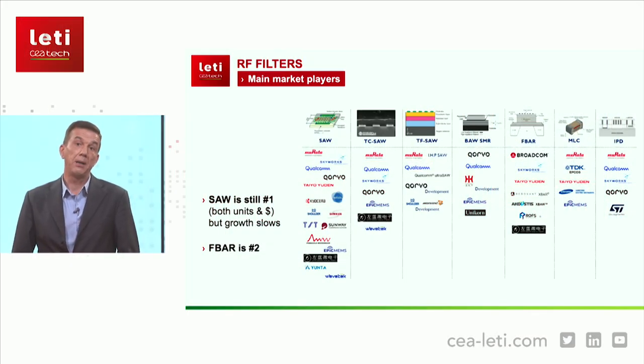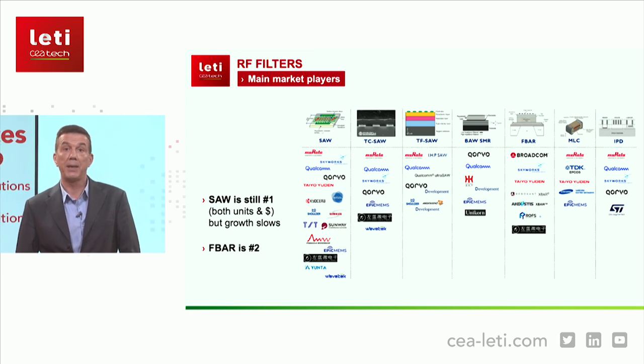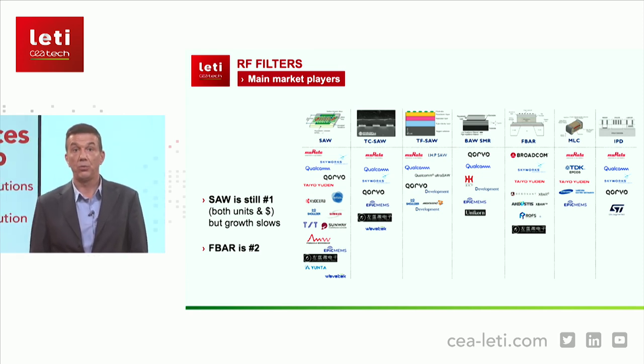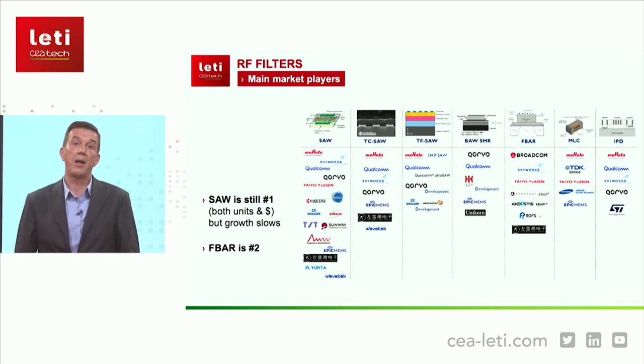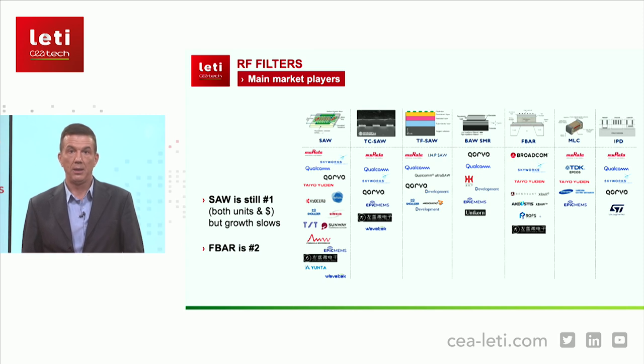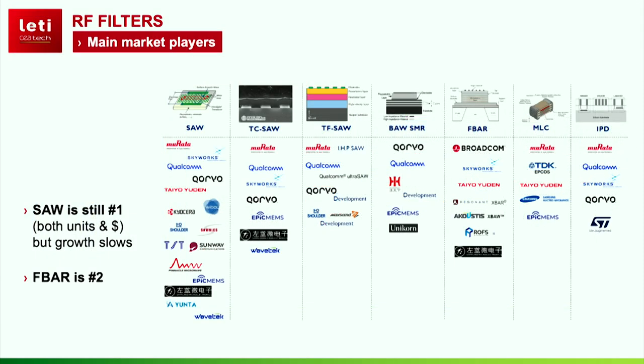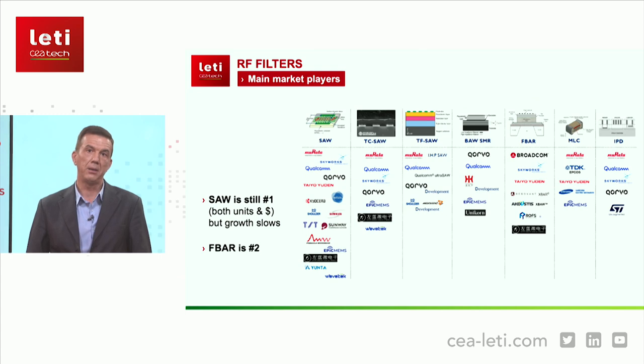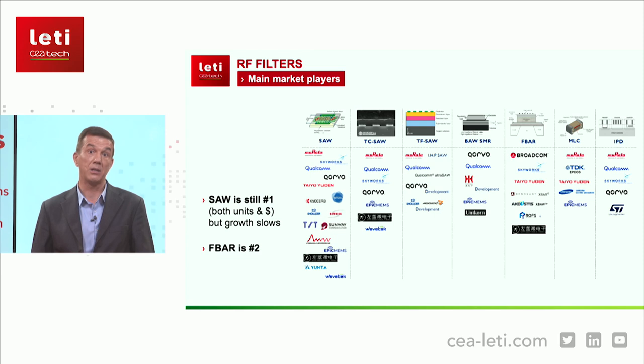RF front ends keep getting more and more complex as new bands need to be accounted for. This translates into more filters being integrated in handsets and also new filter requirements, namely higher central frequency and larger bandwidth. These are the main trends that fuel the filter market growth. The best sellers are still bulk SAW-based filters. They are mainly built using lithium tantalate and lithium niobate bulk crystal. However, thin film-based filters, such as TF-SAW and FBAR, are experiencing important growth and they command higher ASP.